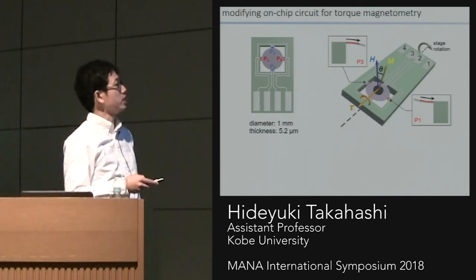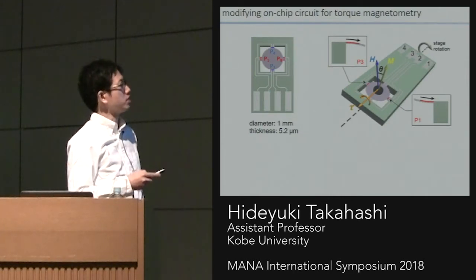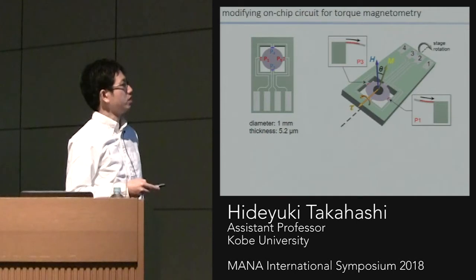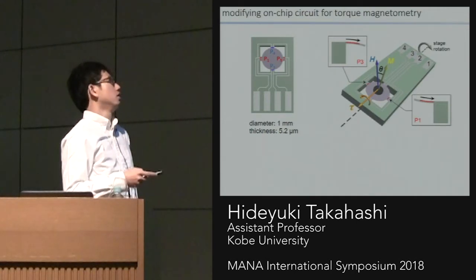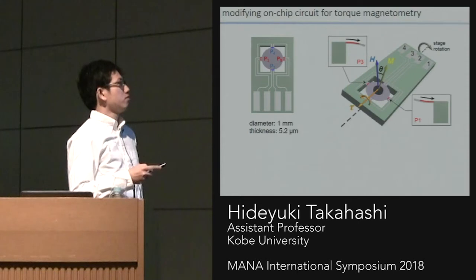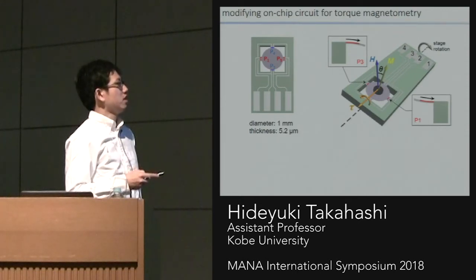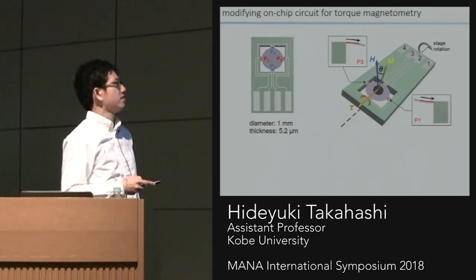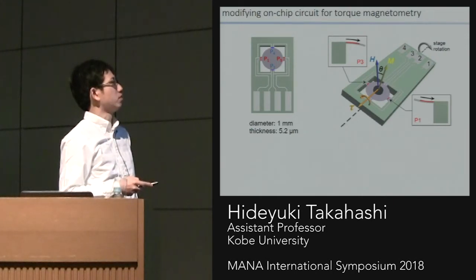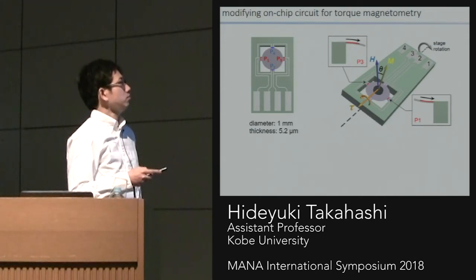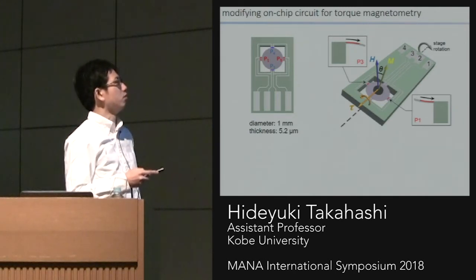Before that, I should explain this chip. This is a commercial chip of MSS, available from NanoWorld. It has a circular silicon membrane here. The diameter is about 1 millimeter, and the thickness is about 5 micrometers. This membrane is supported by four piezoresistive bridges, and we define each piezoresistor as P1 to P4.